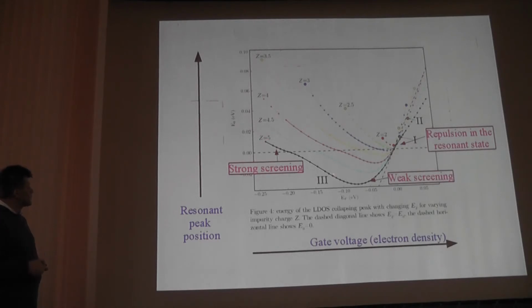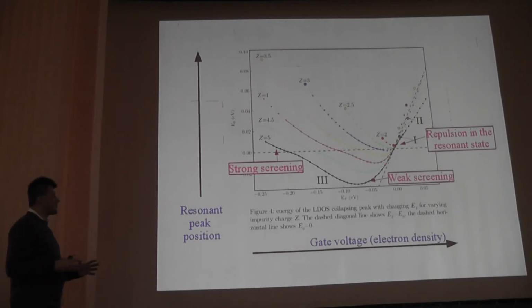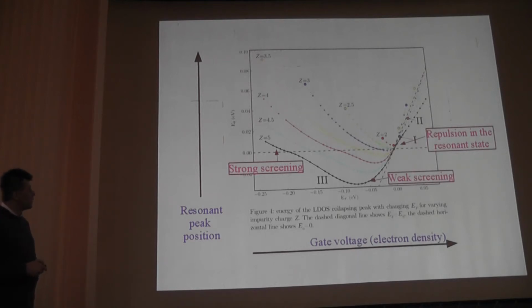Here is the position of the resonance as a function of doping, and you can see that the resonance indeed starts with positive energies, goes deeper as you move the doping closer towards the charge neutrality point, then goes up in energy, and then suddenly disappears on the other side. The explanation for this basically is when the Fermi level is above the resonant level, you have 4 electrons sitting in the resonant state due to high degeneracy of graphene, due to valley degeneracy, K and K prime, and the spin degeneracy. Self-consistent calculations confirm this simple picture.